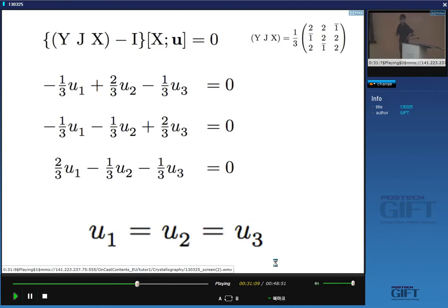6 divided by 3 is 2. 2 equals 1 plus 2 cos theta. So 1 equals 2 cos theta, and cos theta is a half. So theta is 60 degrees. So the two crystals are related by a rotation of 60 degrees about 1, 1, 1.